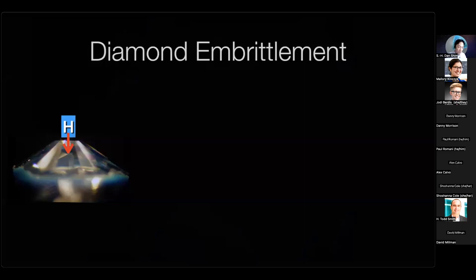Yet there is an important problem of dealing with hydrogen in this experiment, because hydrogen is the lightest and smallest element in the periodic table, as you all know. And it's so small and so diffusive that it tries to find any way to move along the pressure gradient and escape from the pressure chamber. So if you compress hydrogen, it's well known in our high pressure community that they start to diffuse into the diamond. And when they diffuse into the diamond, they go in between carbon atoms and make the diamond structure extremely brittle. And the problem becomes even more severe if you try to laser heat samples inside the hydrogen medium to the melting temperature, which requires heating of 2000 to 3000, even 4000, 5000 kelvins of temperature, depending on the pressure range.